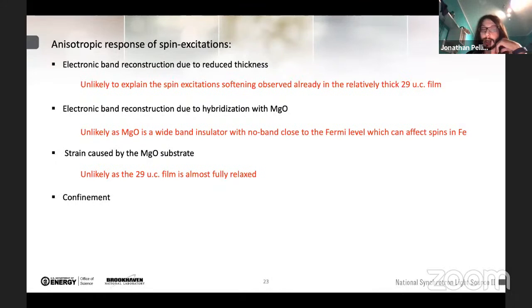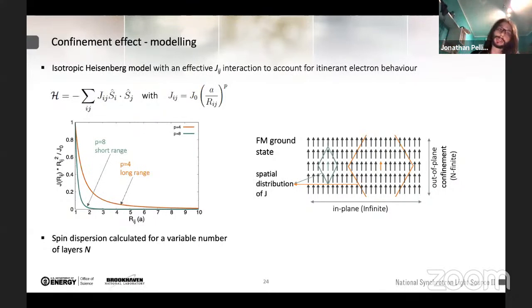So this leaves confinement as a possible explanation for our experimental evidence. In order to further explore this possibility, we asked theoreticians for help and we performed an isotropic Heisenberg modelization of the system, where we used a nearest-neighbor isotropic Heisenberg model, where the exchange interaction was modulated with this formula, where P stands as an exponent for an interaction that would be long or short range, as also shown in this plot.